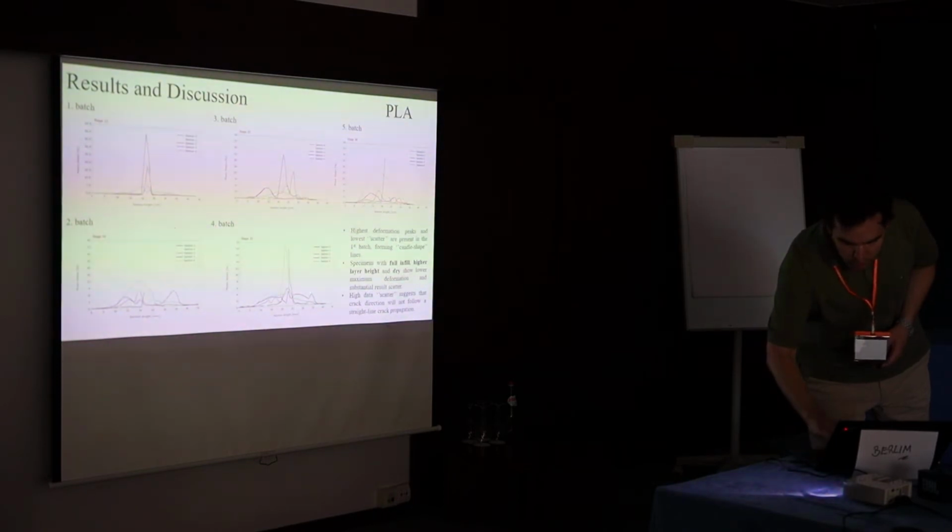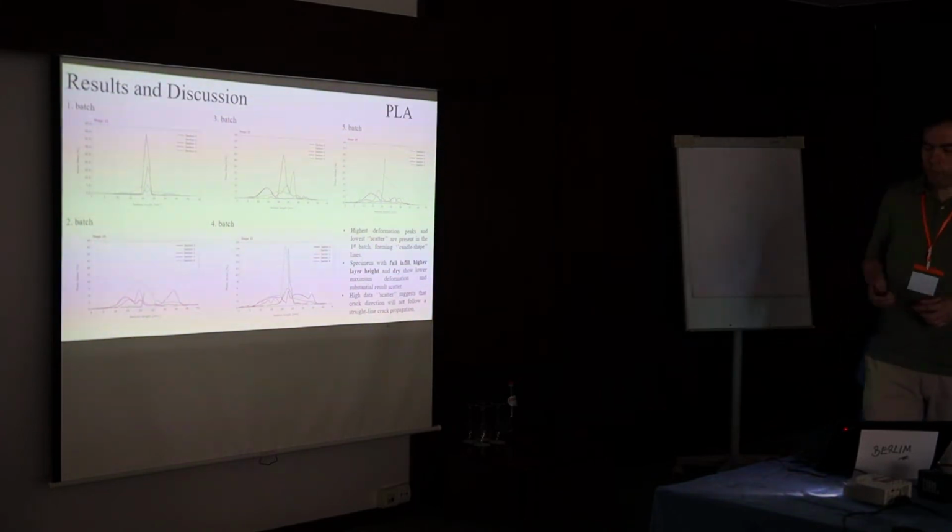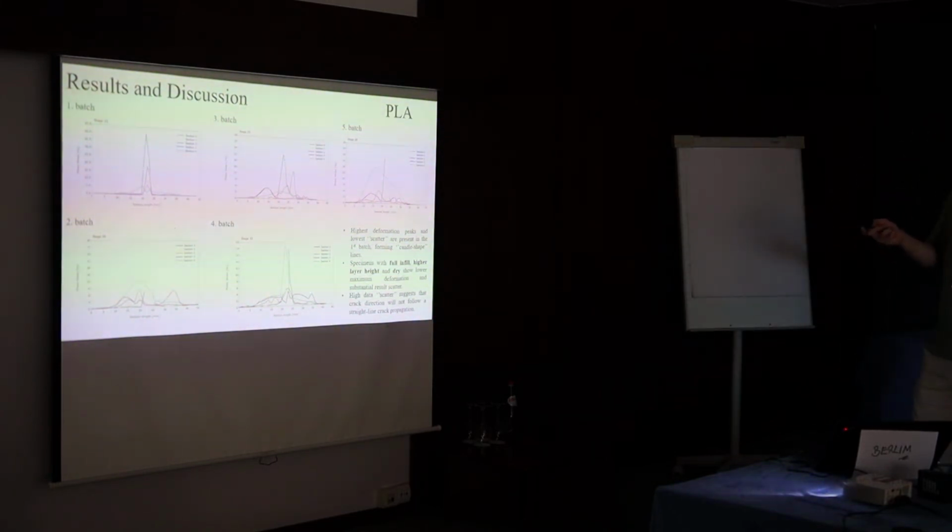Now here are some deformation diagrams. We see that specimens with 50% infill density and 0.1 layer height created so-called candle-shaped curves on these deformation diagrams.